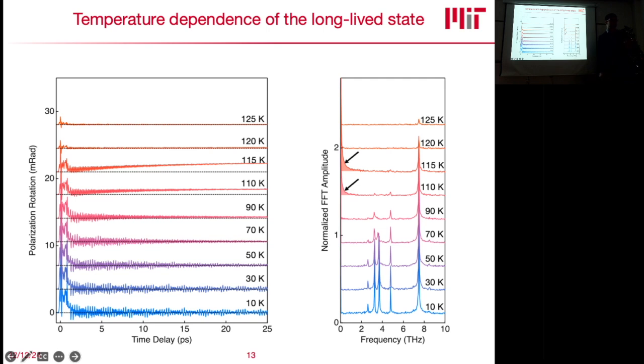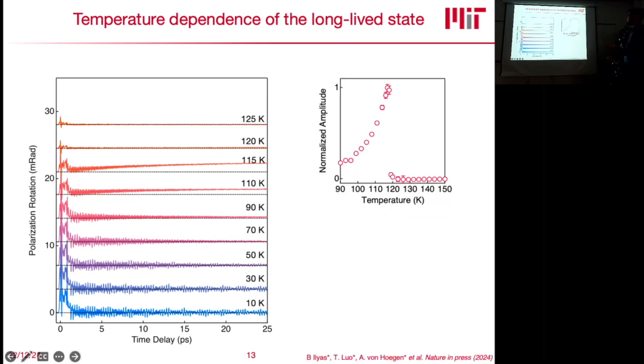So this was very exciting for us, because that kind of means that this now stronger spin-lattice coupling close to the transition temperature actually leads to some sort of long-lived modification of this magnetic ground state. So this was very exciting to see for us. And so if you take a full temperature dependence of this, you get something like this asymmetric shape. So it peaks at the transition temperature and then it's basically zero above.